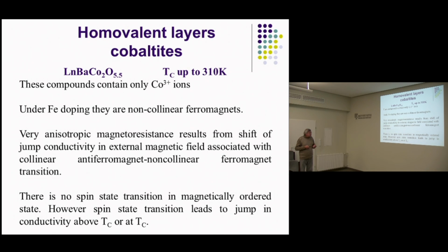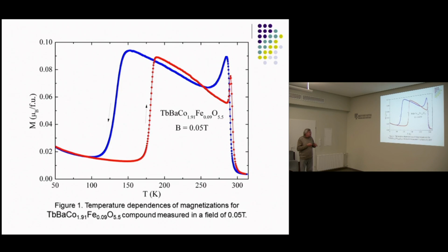We show that the ground magnetic state may be either antiferromagnetic or non-collinear ferromagnetic. The transition between non-collinear and collinear antiferromagnetic leads to a jump of conductivity and is associated with large magnetic resistance, because an external magnetic field shifts this transition to lower temperature. It was published at first in Physical Review Letters.